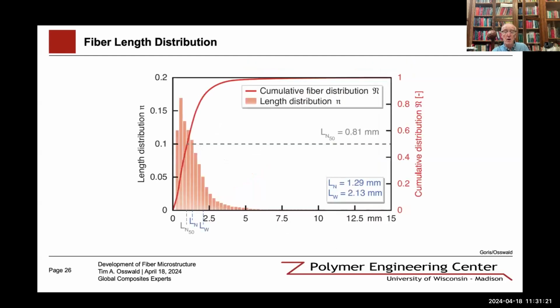So how do we represent fiber length? Typically, what we look at is the fiber length distribution. That's the histogram that you can see on the right-hand side of the graph. This would be a typical plate injection molded with Stamax, which starts out at 15 millimeters. And there are some fibers that are retained at long lengths, but most of the fibers are in the shorter range, 1 millimeter or so. If we take the fibers and do a number averaging in this distribution, we have about 1.29 millimeters in fiber length. The weighted average, which means the longer fibers count more than the shorter fibers, is about double that length.